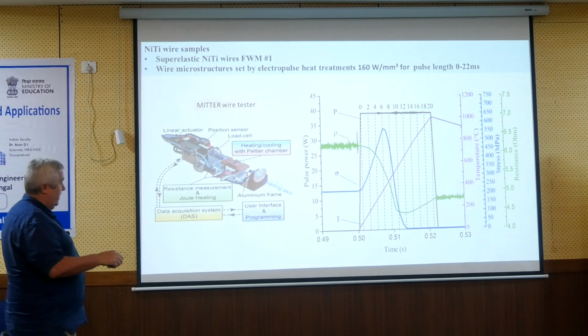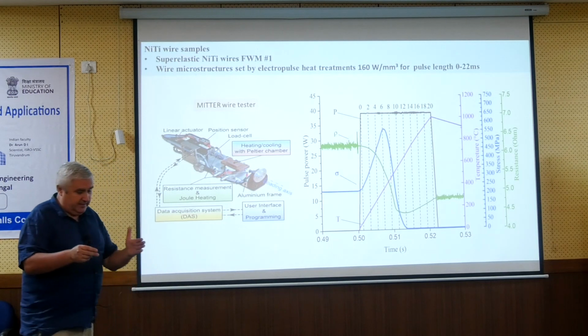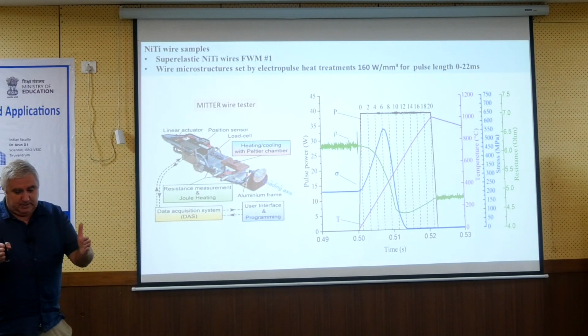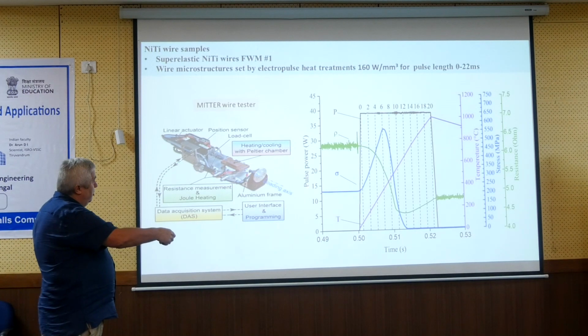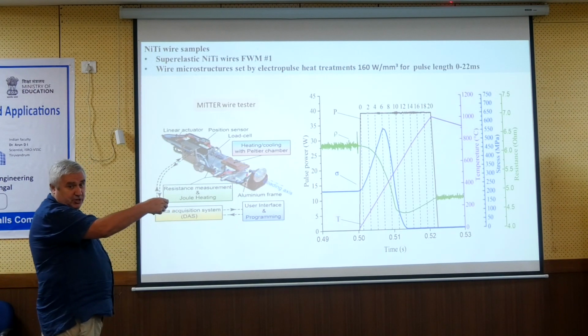Now, if I should answer, as I said, you have the wire. The wire is pre-strained and the length is fixed. Now there is martensite in it, and we are heating. When we are heating, martensite wants to shrink, so the stress goes up. And if there is only this process, it will go up forever until it fractures.